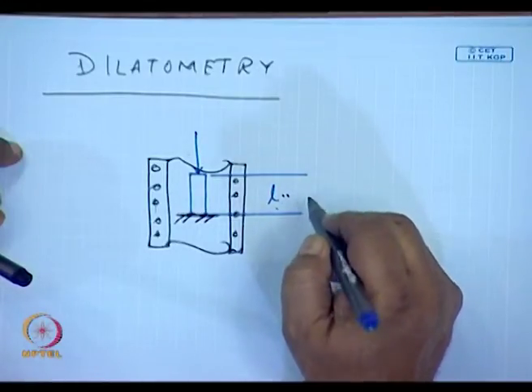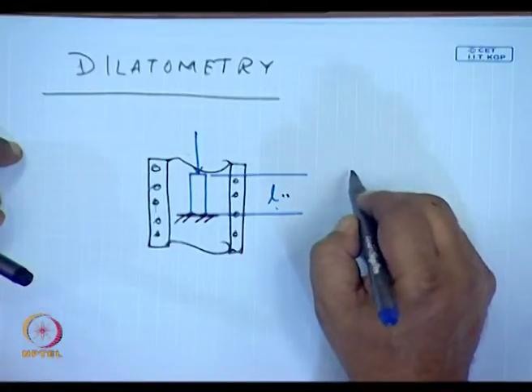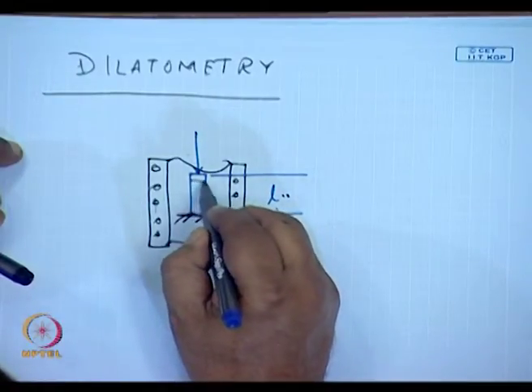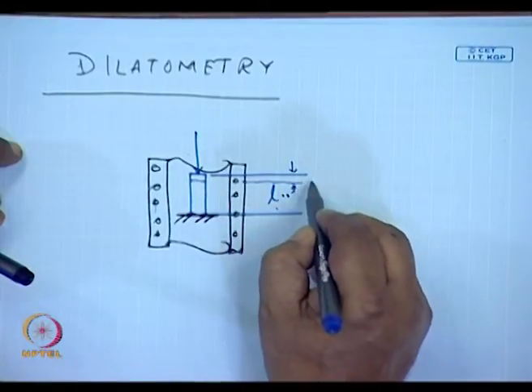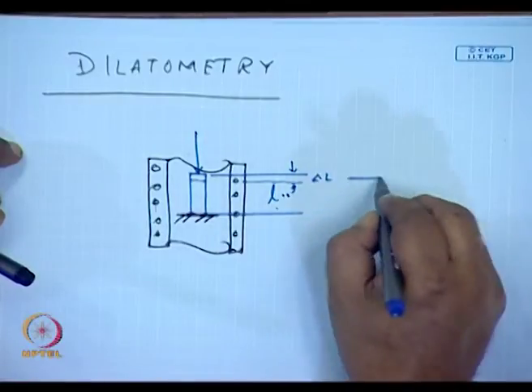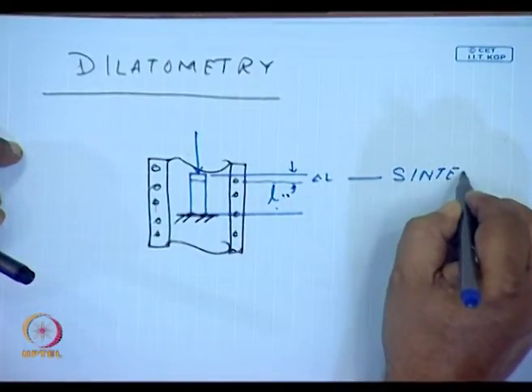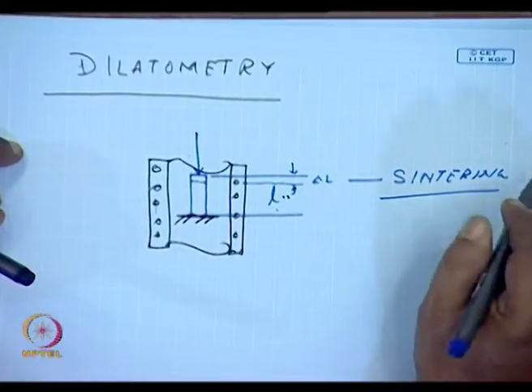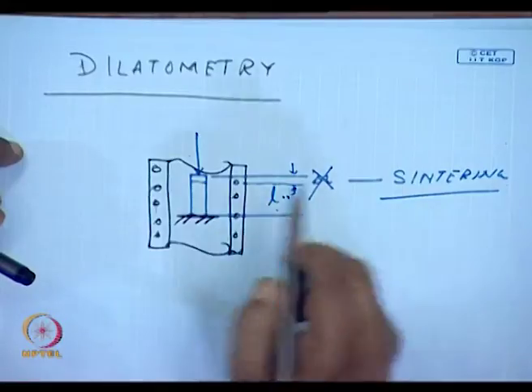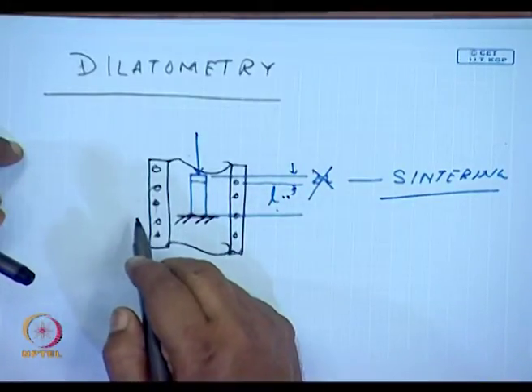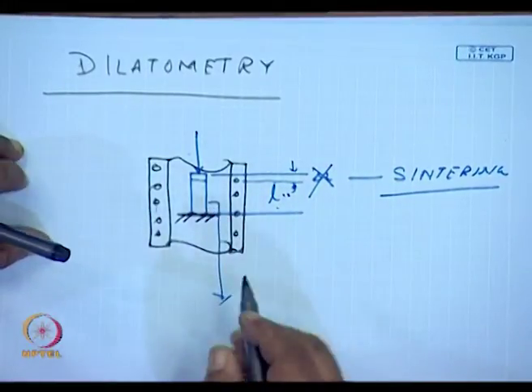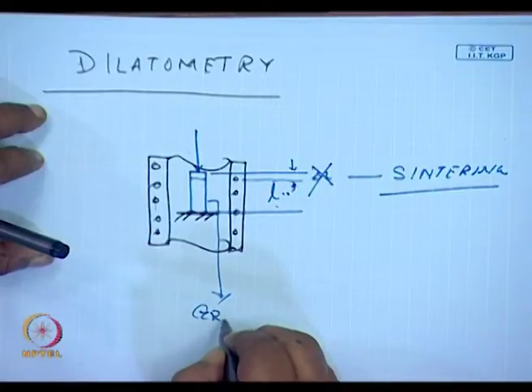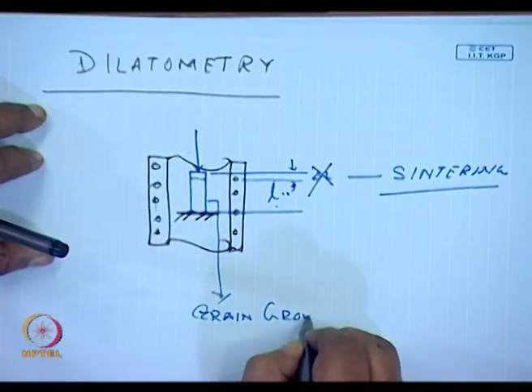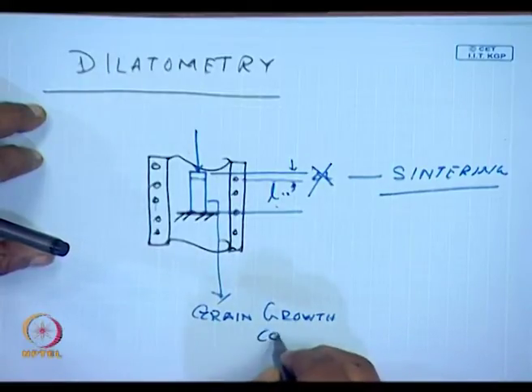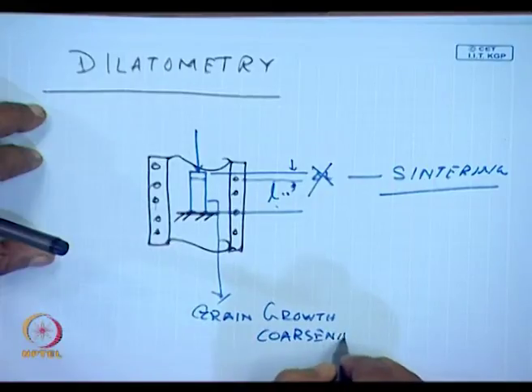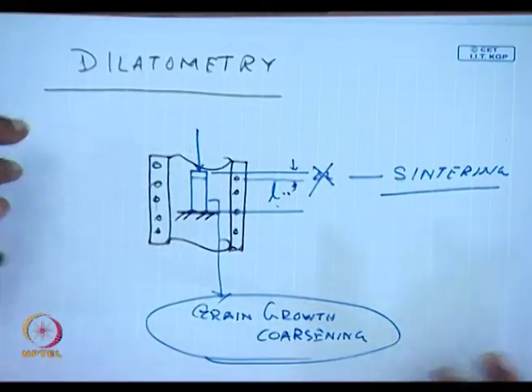At the end of the day, at the end of the temperature, if the final length is somewhere over here, that is, a shrinkage has occurred to the extent of del L, only in that case you have sintering. If this had not occurred, if the length had remained unchanged, it would have meant merely grain growth, coarsening, etc., where no dimensional change has occurred.